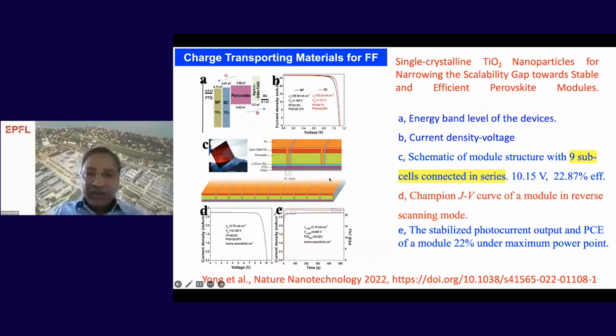So we increase the size of the cell. This is a very small cell, and then we increase to 24.63 centimeters squared, and the efficiency is 22.87. So we have 9 subcells.